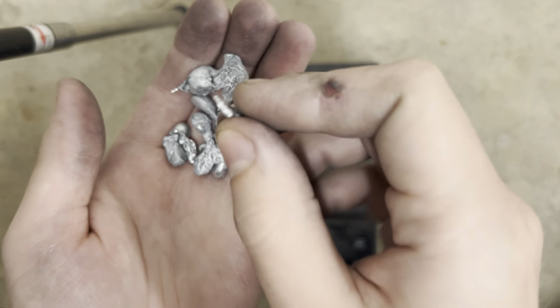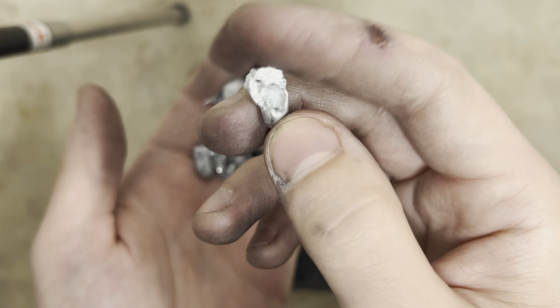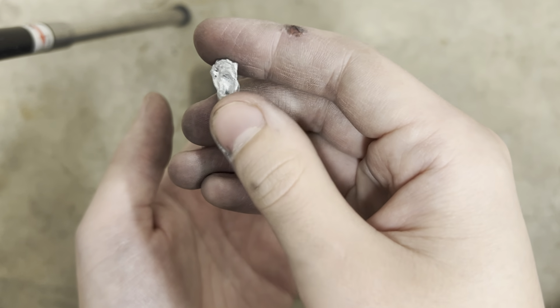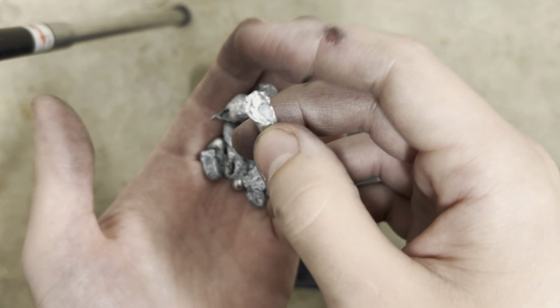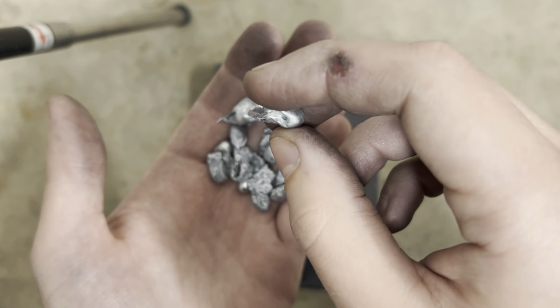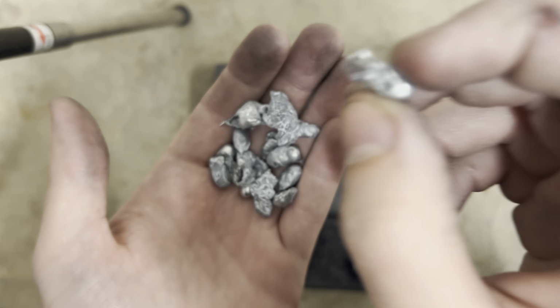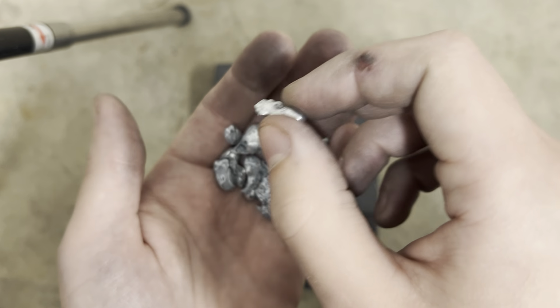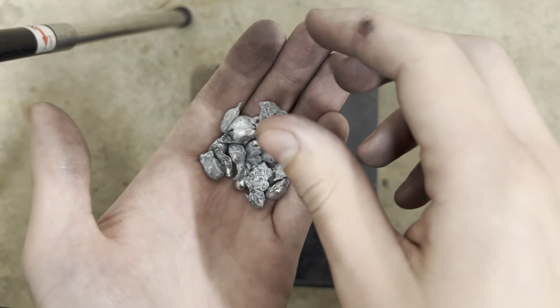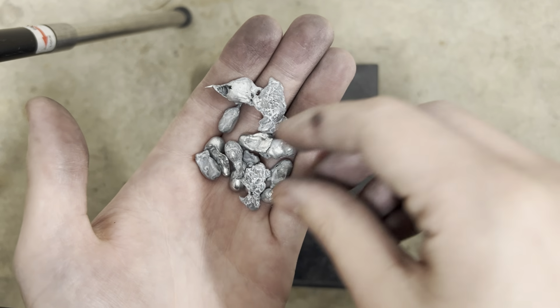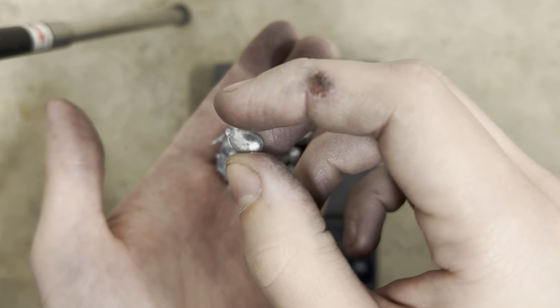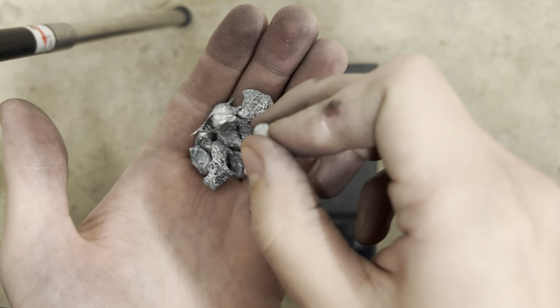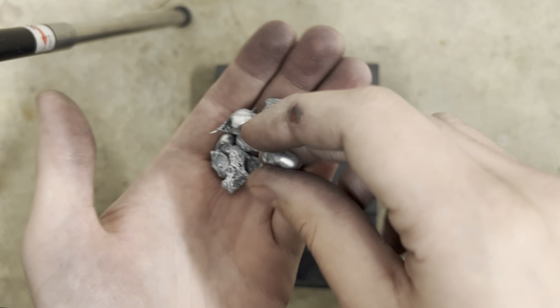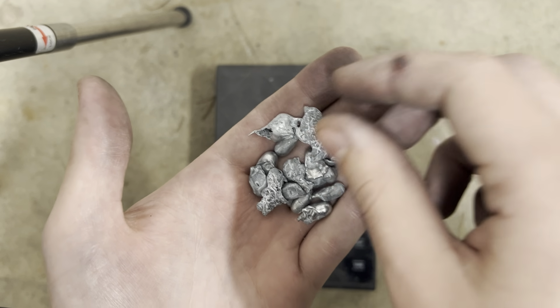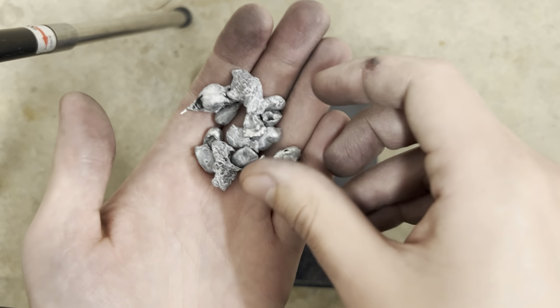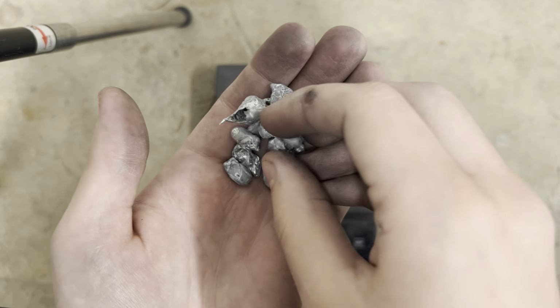So what this does is it allows us to add our zinc piecemeal. By adding just a little tiny piece, which weighs anywhere from like 1 to 5 grams, I think, from what I measured these, it will drop down into the molten copper and melt and dissolve into the copper almost instantly. And instead of sitting on top, it'll get absorbed into the copper and begin the alloying process, and we won't have to deal with nearly as many fumes. In addition to that, by adding it this way, it means that less zinc is going to be lost to oxidation and boiling, meaning that your alloy will be as close to the exact proportions that you wanted it to be as it possibly can. Some zinc always burns off. It's kind of unavoidable.